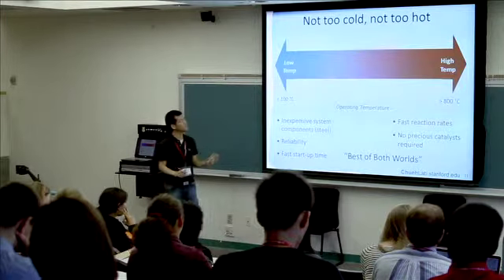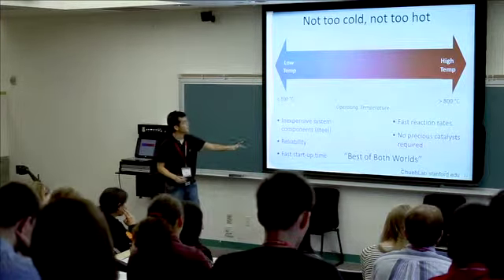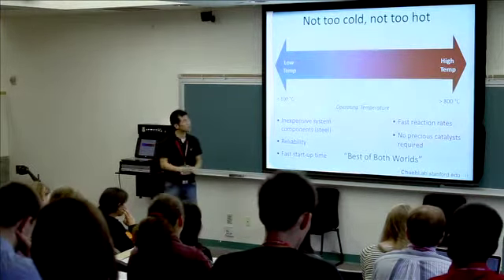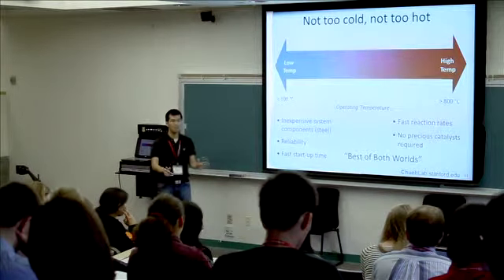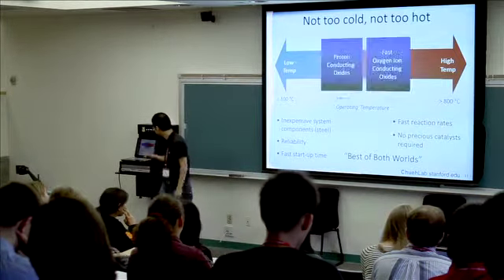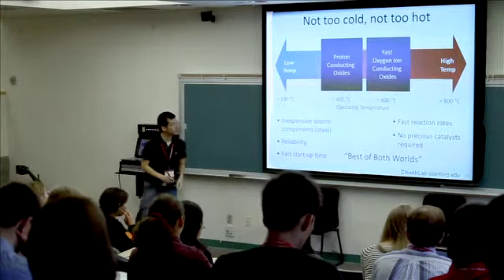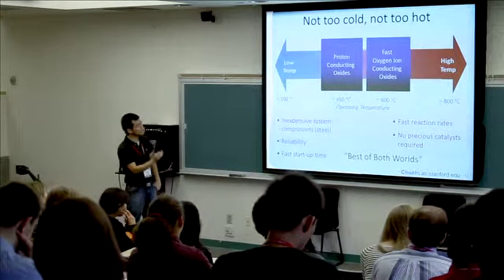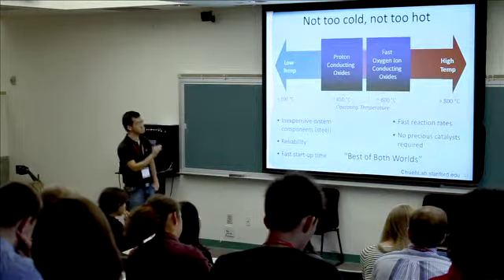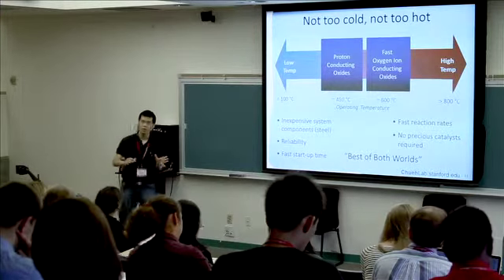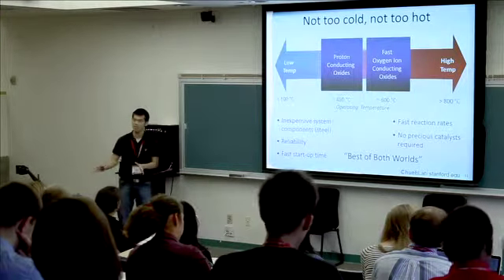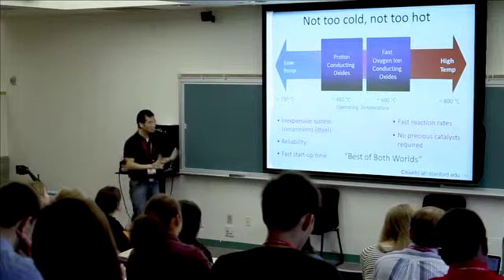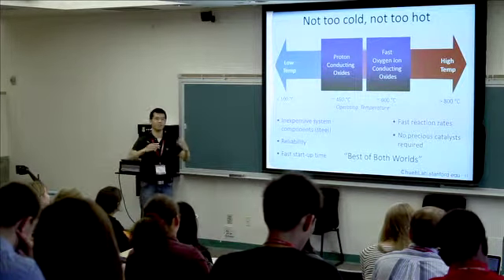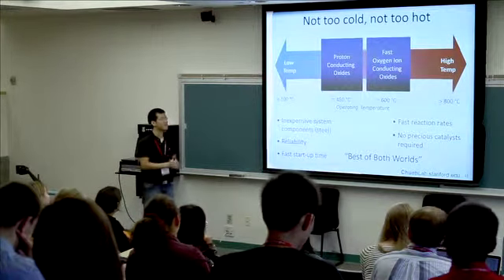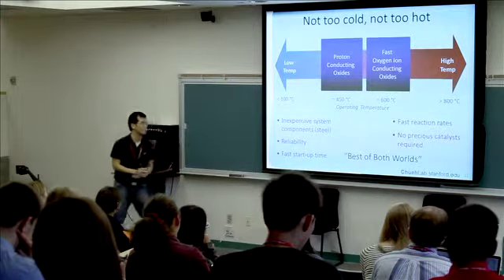We wanted to have the advantages of the high temperature and the advantage of low temperature. So it turns out we need to operate somewhere in between. And the type of materials that my group is interested in, we're looking at material that can work at about 400 to 600 degrees Celsius. So this is the range where you can still use stainless steel as an enclosure material, and you can still leverage all the benefit from accelerated reaction kinetics and lessening the requirement of precious metal catalysts.